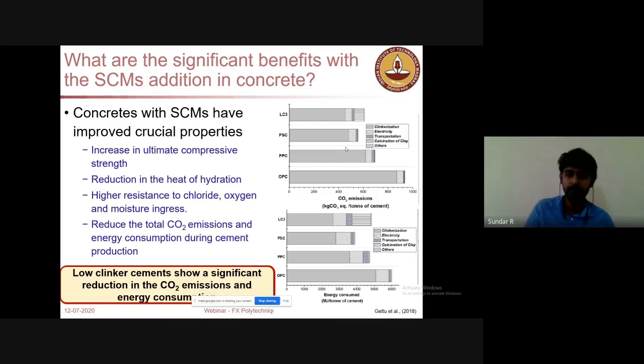This high resistance to ions is very important from the point of view of durability. Next we will see how CO2 emissions are controlled. The main purpose of adding SCMs initially was to reduce total CO2 emissions, and that has been solved by adding SCMs. If you look at regular OPC, PPC, Portland slag cement, and even new cements with elements like limestone calcined clay cement, the blended cements always show much lower CO2 emission than ordinary Portland cement. Energy consumption during cement manufacture is also very high for OPC, and it has been reduced for mixes like PPC, PSC, and LC3. This is the addition of SCM that has been observed in our industry.